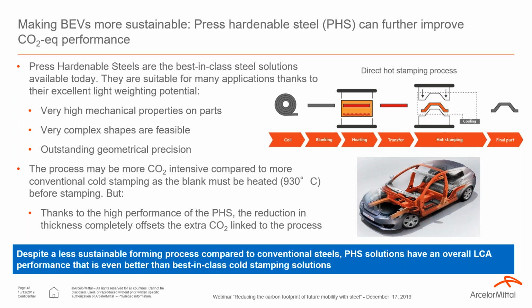It means that you are not only able to produce very complex shapes, but we also master the conformity of parts. On the other hand, we have a kind of drawback regarding the CO2 emission, because compared to the conventional stamping process, we have to add a heating step to heat the blank prior to the stamping process, with the objective to reach a temperature of more than 900 Celsius and keep the blank in the furnace for approximately 5 to 6 minutes. But at the end, when we look at the performance of the part, the lightweighting the part is able to bring completely offsets the CO2 equivalent emission linked to the heating phase in the furnace. This is why today we are confident to say that in many applications, PHS solutions bring further CO2 equivalent emission reduction.